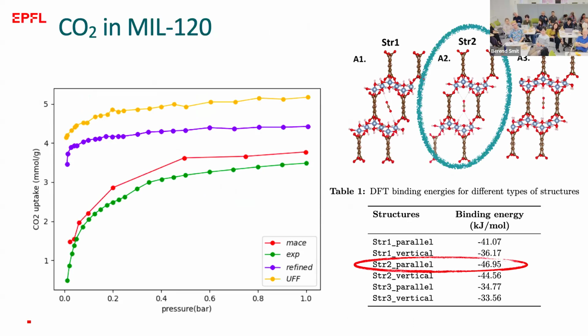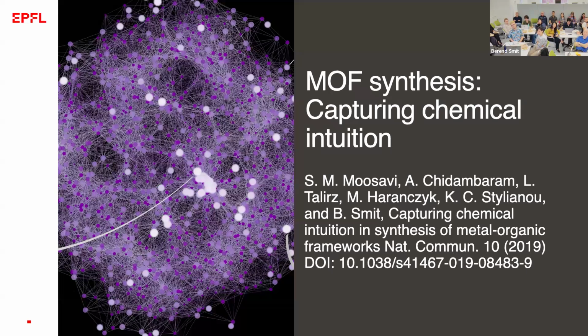So what you see here, this is the CO2 molecule. Here are those hydrogen bonds. It optimally forms 4 hydrogen bonds in the minimum energy configuration. But as soon as you have some thermal motion of the hydrogen bonds, it loses that optimum configuration. So this very high adsorption is done with a rigid crystal structure, where by accident it was optimal for the CO2. Of course, the force field was correct, but we didn't take the movement of the hydrogens into account. That is the reason why it drops so much, and also why water is so difficult to simulate. It's not very large vibrations, but simply small changes in the orientations of the hydrogens in the metal organic frameworks, which you really need to capture, and you can capture that very well with those machine learning force fields.